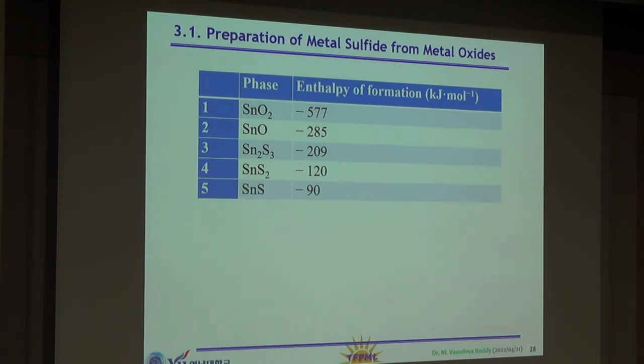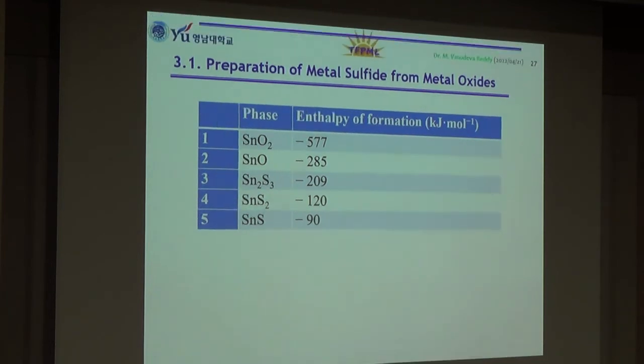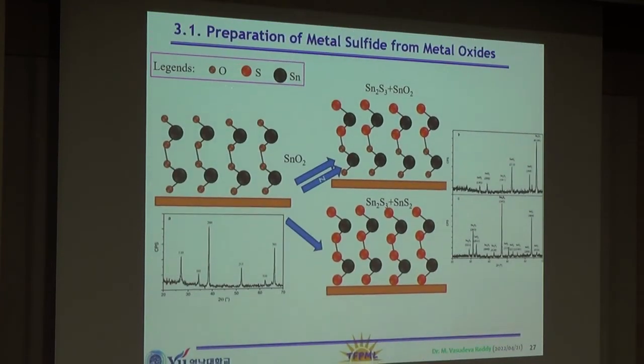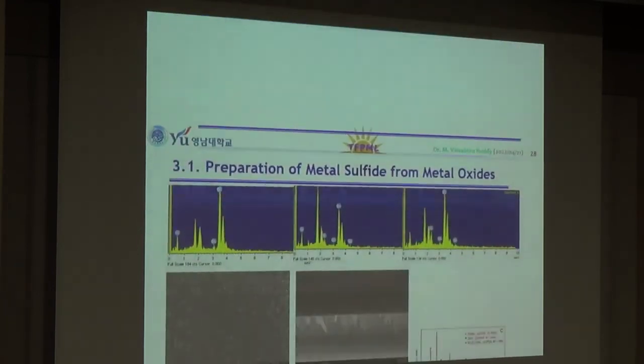This process also seems to be similar. We tried a wide range of temperatures, from room temperature to around 550 degrees, but we were still unable to form tin monosulfide. Instead, we are getting either tin disulfide or other phases.